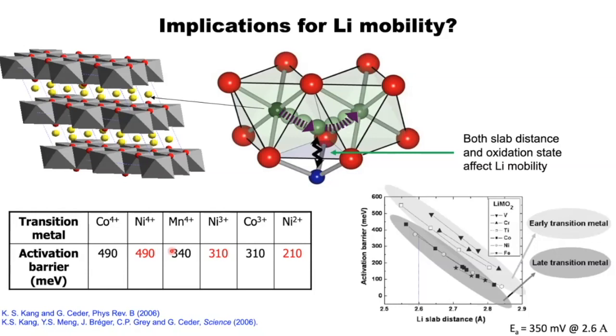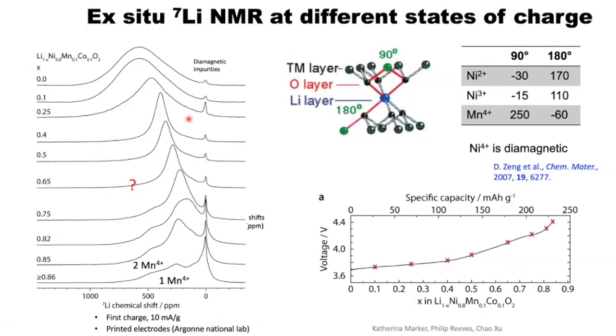What we then did was to examine the materials by NMR. What we're doing now is to use ex situ NMR. What I mean by that is we make lots of different batteries, we stop them at different states of charge, we pull them apart and we do NMR spectroscopy. We're doing lithium-7 NMR, and when we start, the initial material contains a very broad signal. It's broad because the lithium sees a whole variety of different transition metal ions in the layers above and below. For a number of years, we've developed an understanding of how to interpret these NMR spectra in terms of the numbers and types of paramagnetic ions.